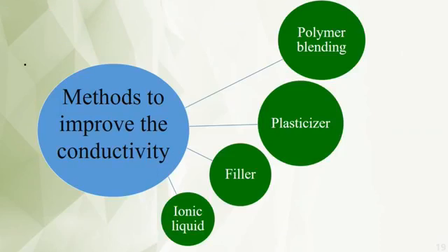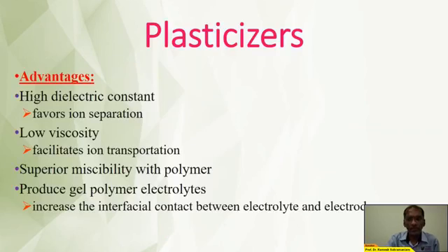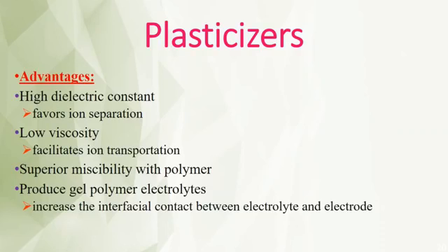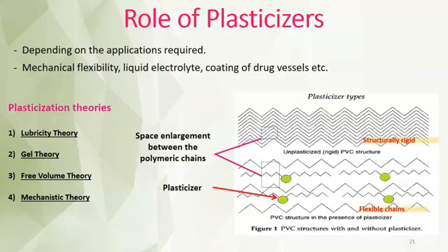Okay, here I'm also sharing with you all what are the methods that we can use to improve the conductivity, like polymer blending, plasticizers, fillers, and ionic liquid. Okay, the first one will be the plasticizers. So plasticizers generally give us a high dielectric constant. Once they have the high dielectric constant, this will be a good advantage to increase the conductivity of the electrolyte system. On top of that, they also show a low viscosity and superior miscibility with the polymer to produce gel polymer electrolytes. So here we can see the role of plasticizers.